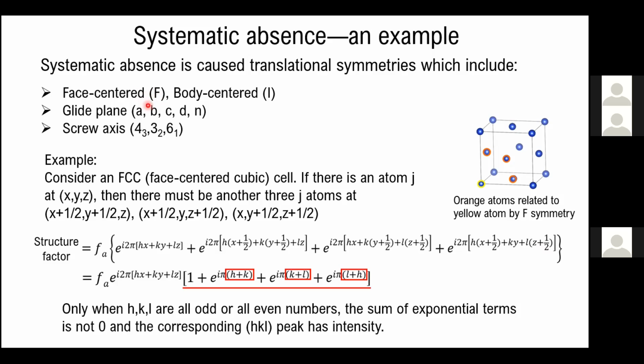So what I mean by translation symmetry is, let's say, look at this simple FCC. This could be nickel, right? So all the copper, which are all FCC structures. For example, if this is nickel, and we have an atom here, this is 000, right? Because this unit cell has Fm-3m symmetry, starting with F, that means it will definitely have a symmetry equivalent atom here, here, and here. Those are all the face centers, right? And they must be exactly the same atom as what we have here.